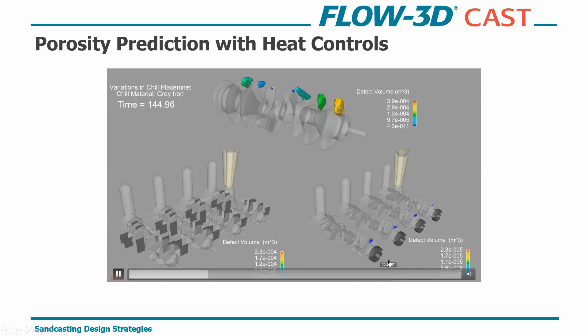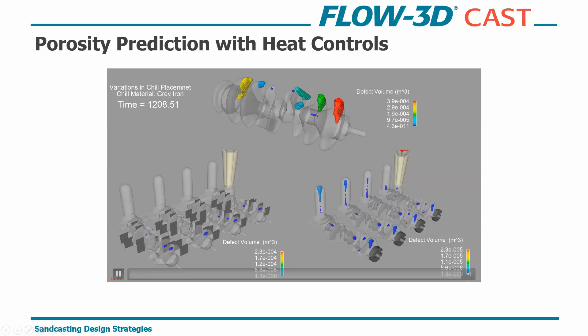Lastly with this case, to showcase more functionality, we look at the principal shrinkage model with porosity prediction and heat controls. We've added riser sleeves and different types of gray iron chills — fin chills and ring chills on the ends. Comparing preliminary solidification results: with ring chills, porosity moves away from the end but slightly into the part; with fin chills, we see much less porosity formation and it's moved away from the edge. Based on your product specifications and tolerances, this could be the effect you want.